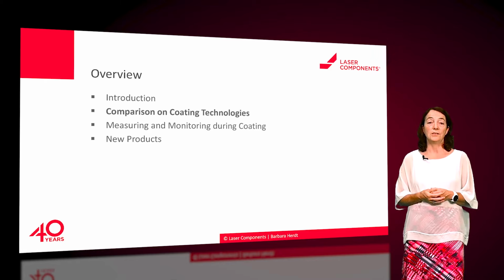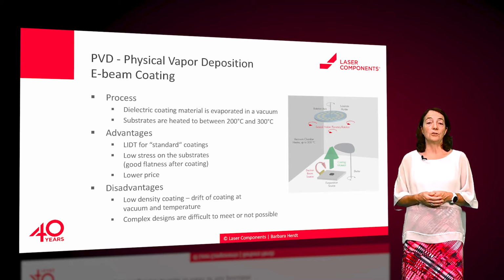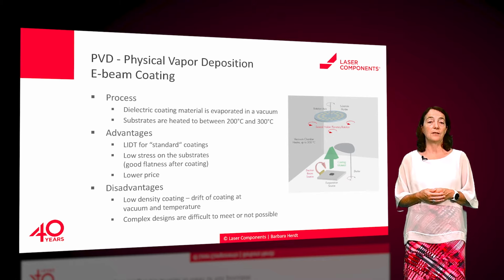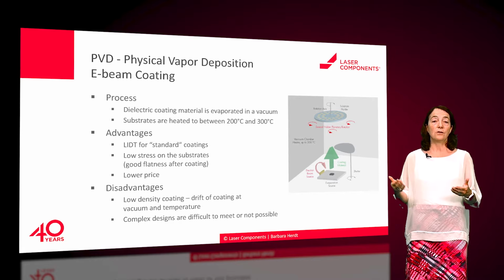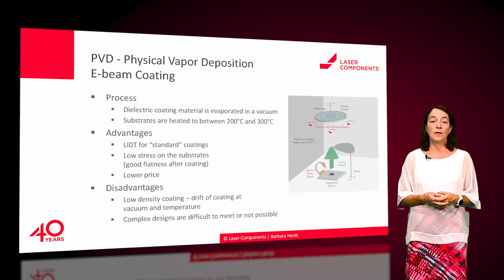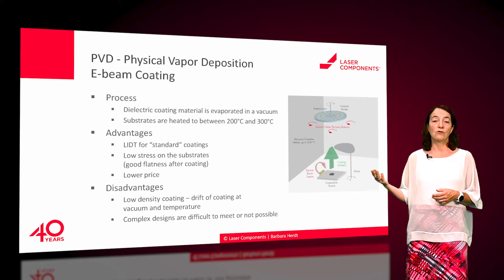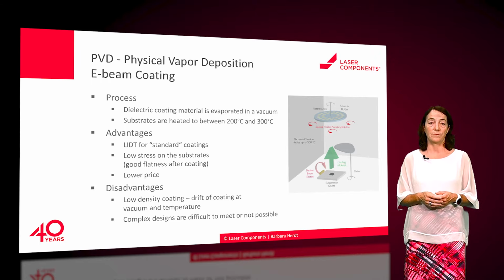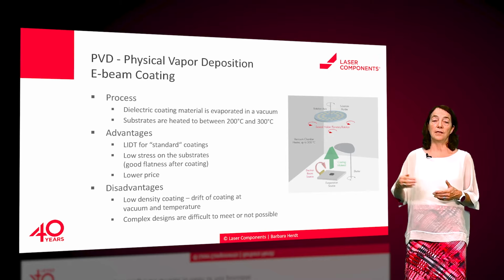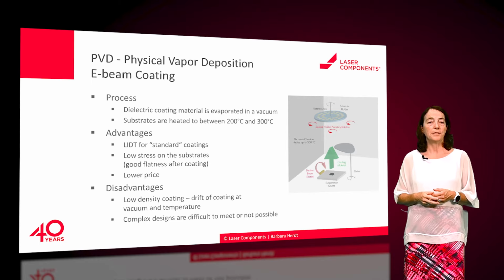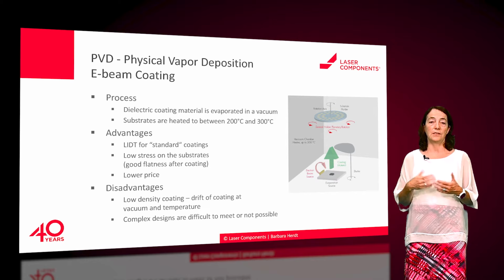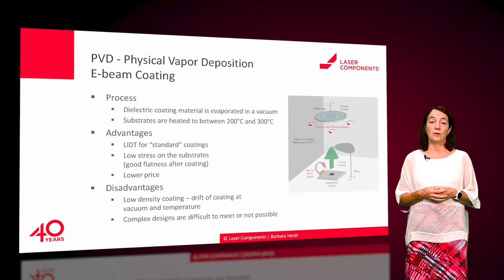When comparing the coating technologies, I will talk about the 3 technologies we are using for our high-power laser optics coatings. The E-beam technology, also known as PVD or physical vapor deposition coating, has been used since the beginning of laser optics production. How does it work? By heating the coating material with an electron beam, which is where it got its name from, the coating material evaporates. This is done under vacuum and the molecules from the coating material deposit in the chamber. In our case, we use a chamber with the coating material at the bottom and the substrates at the top in a planetary rotation system to get a homogeneous layer thickness over the area. To reach a good adhesion of the coating material on the substrates, they are heated up to about 200 to 300 degrees Celsius.